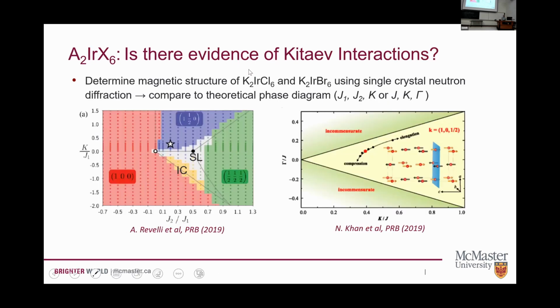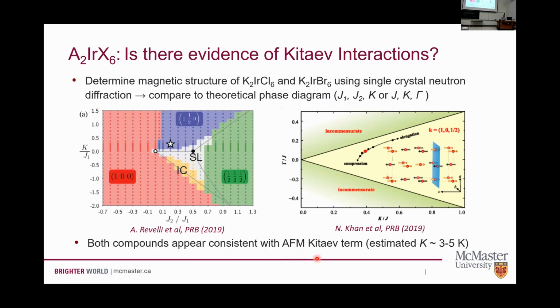Okay, so you can do the same game, studying the magnetic structure, mapping it onto these theoretical phase diagrams. And as in the double perovskite case, what you get is something that looks consistent with an antiferromagnetic Kitaev interaction term. Okay, it's a relatively small energy scale. It's about 3 to 5 Kelvin, but it's not so different from the strength of the Heisenberg exchanges there.